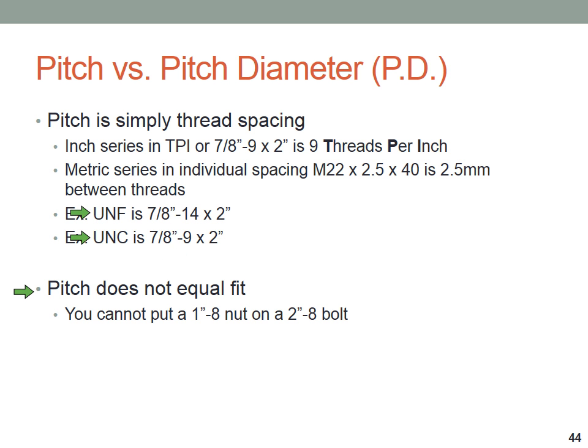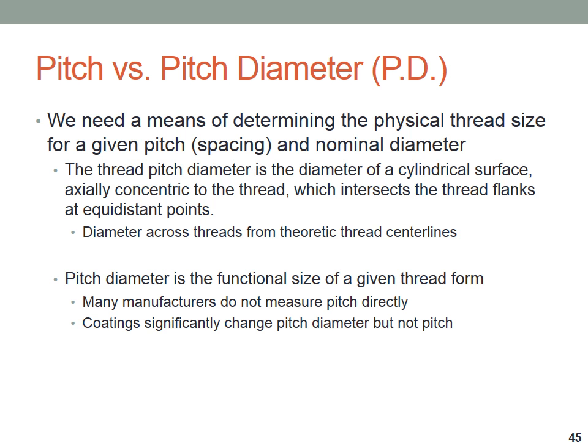Pitch does not equal fit, however. Implying that pitch equals fit would suggest that you could put any diameter of bolt on any fastener that met the same pitch. A very simple example of that is you cannot put a 1-inch 8 nut on a 2-inch 8 bolt. It simply doesn't work, even though they have the same number of threads per inch. It's very obvious why it doesn't work, and yet you can get each of those in an 8 thread per inch variant.